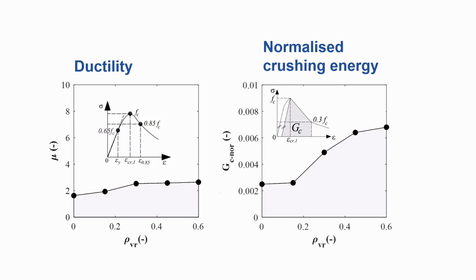So this again was determined from the stress-strain response by the shaded area shown there as GC. And just to allow non-dimensional comparisons, we divided that by the compressive strength. And as the rubber content in the concrete increases, we see an increase in the normalized crushing energy.